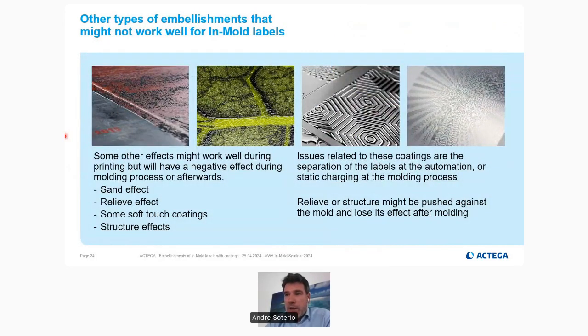Other types of embellishments might not work well for in-mold labels. We have done some trials in the past, and we could not get good results. Some of the effects that we tried are a sand effect, which can be used really well on a pressure-sensitive or self-adhesive label, a relief effect with silkscreen, some soft touch coatings, and some structure effects.